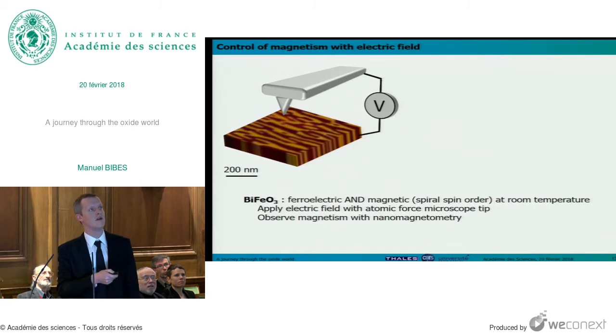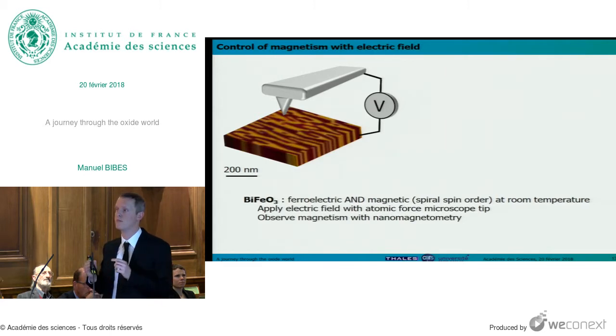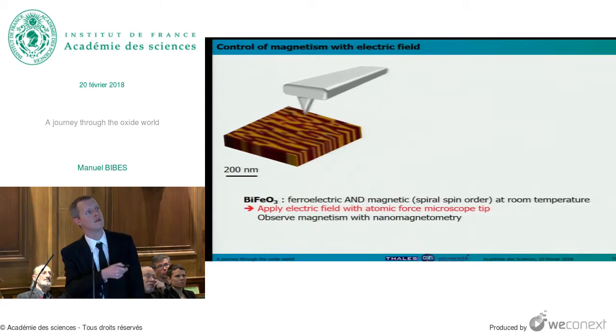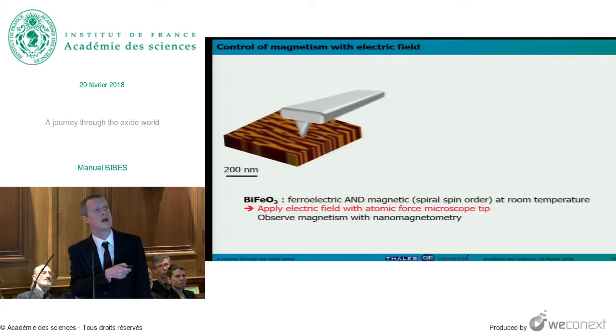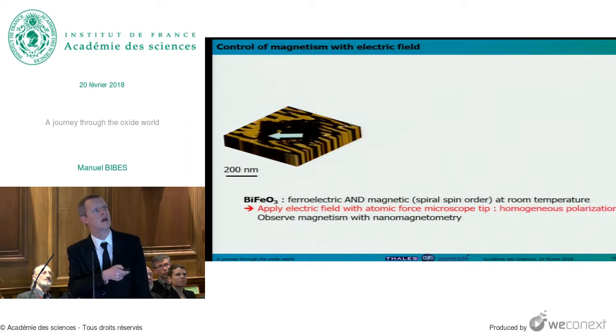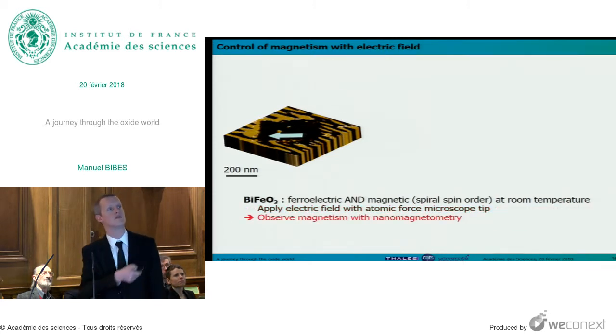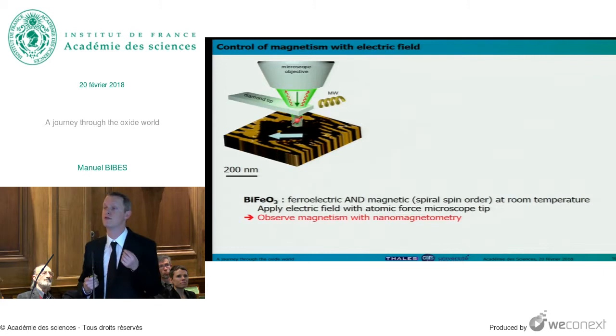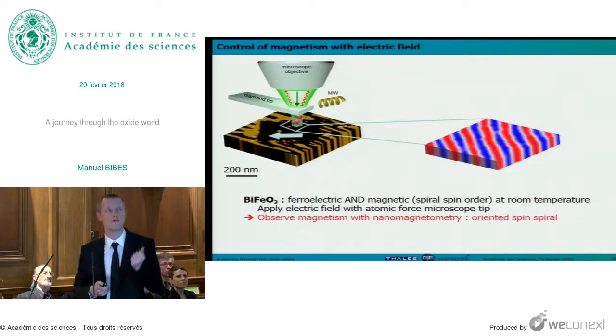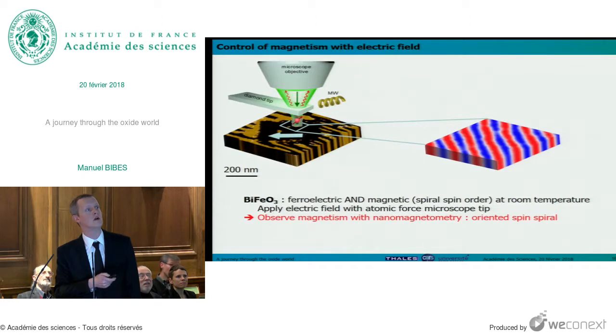This is an image of our sample. The yellow and brown regions here correspond to regions where the polarization of the ferroelectric is along different directions. This is a bit complicated. So we use a very sharp tip to apply an electrical voltage and induce the presence of just one single domain region. Here we have a region where the polarization is homogeneous, say here along the left. And then we want to see what happens to the magnetism in that region. So we use a different microscope. And this is a collaboration with a group in Montpellier.